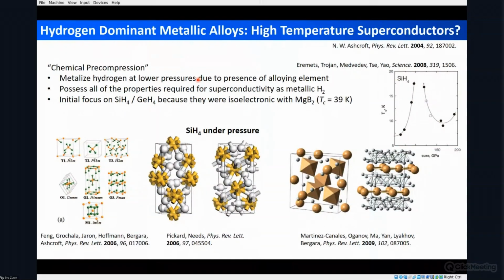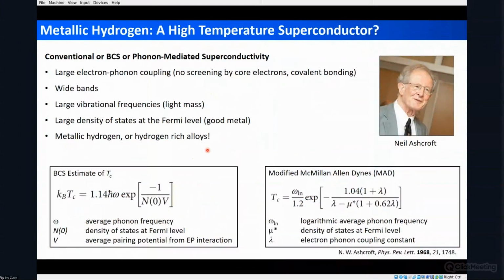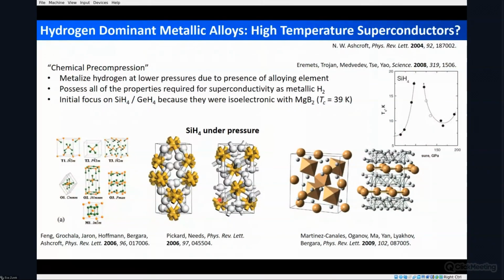So afterwards, Neil Ashcroft proposed, because you can't metallize hydrogen at low pressures, and metallization at high pressures, though it has been achieved, it has undoubtedly occurred at high temperatures, but at low temperatures, there are a number of experimental challenges. For example, the hydrogen reacts with the diamonds in the diamond anvil cells, so you have to coat it, and there are a number of challenges associated with characterizing whether or not you have achieved a metallic state. So Ashcroft proposed that potentially we could lower the pressure associated with metallization by doping with another element.